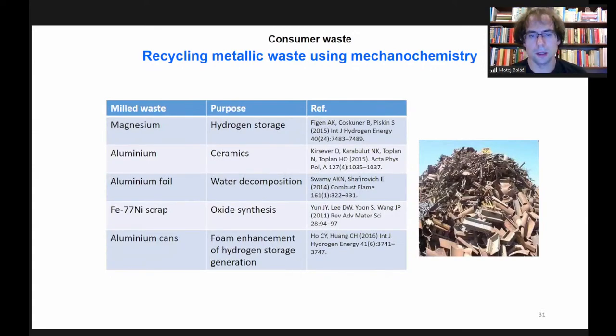Then there is also another metallic waste, but it cannot be considered electronic, because usually we are talking about some chips, for example, that are produced upon the production of products from magnesium or aluminium during processing, or also, for example, when steel is made, we also have waste with a lot of iron. And this is just an overview table to show you what the produced materials can be used for. So we have some metallic chips, for example magnesium, and after mechanochemical treatment, we can efficiently use it for hydrogen storage. Or we have some iron containing waste, and because of the efficiency of the milling procedure, we can transform it into iron oxide nanoparticles, which can be applied, for example, for adsorption.